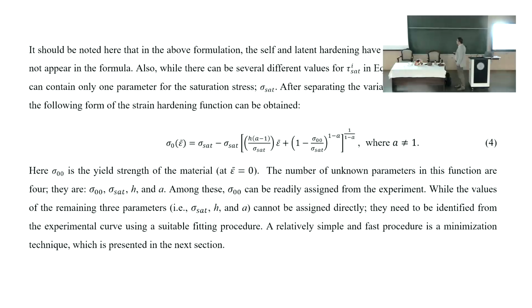And there are 2 numerical parameters, the H here and the A, which is appearing at 3 different positions, you see, in this way. So that's the empirical function we found in this way, and that's what we are going to use now, to see how it is performing on fitting macroscopic curves.